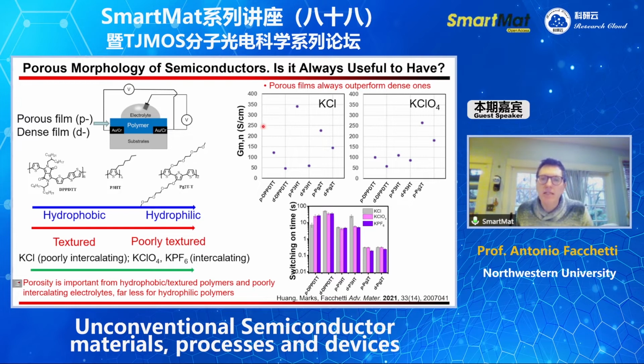And these are some of the results. There is a lot of data, and I don't have time to discuss it all, but this is the transconductance, and you want to have it as large as possible. What you see here is the transconductance when we use the chloride, which is poorly intercalating, and this is when we use the other 2, which are very intercalating. And what you see is, first of all, the porous structures, which are these points here. I'm sorry, I should have put different colors. They are always larger compared to the dense films, which are these ones. So it means porosity always enhances the transconductance to a certain extent.